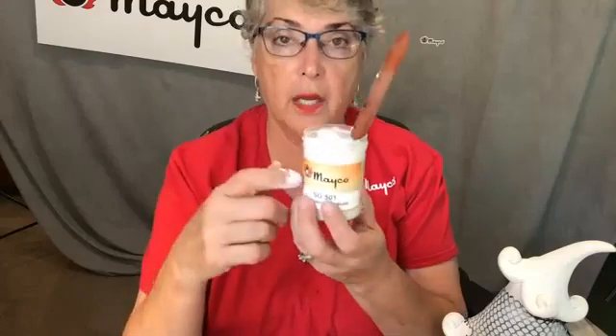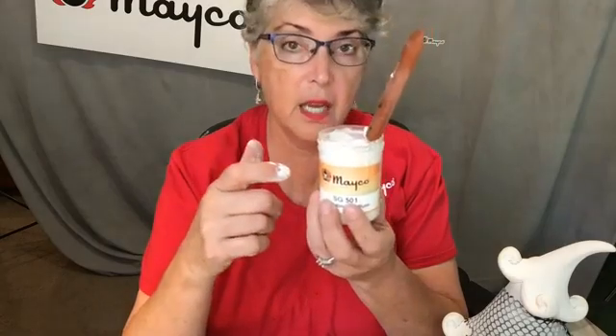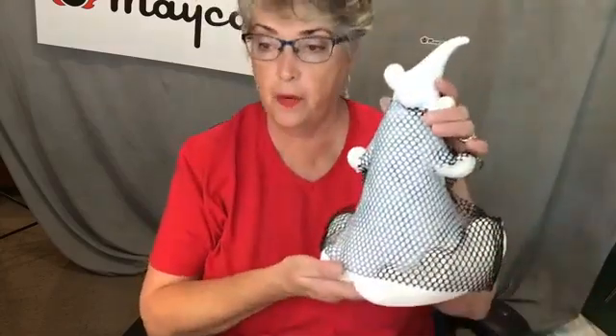Now, one thing you guys remember, whenever the product is textured, you don't use it on a food surface. So you're not going to take this technique and put it in the center of a bowl or where the mouth would touch on a mug. It wouldn't be here. You could do it down here. That would be fine. And not in the center of the plate. You could put texture on the rim of the plate, but you don't want to put a textured product anywhere that the food is going to be, or you're going to hit it with a knife and fork, because it'll trap bacteria. And since we're not supposed to put earthenware in the dishwasher, it's very difficult to sanitize. That is Mayco's opinion. All right.